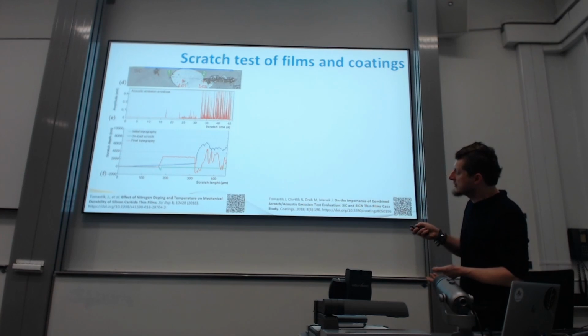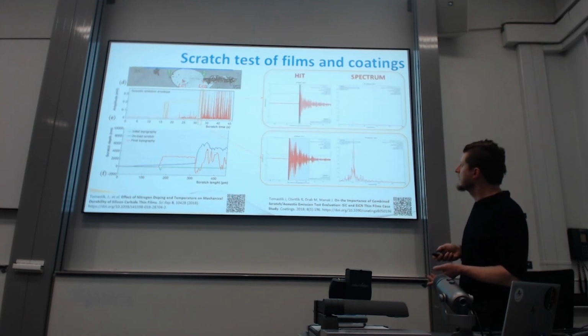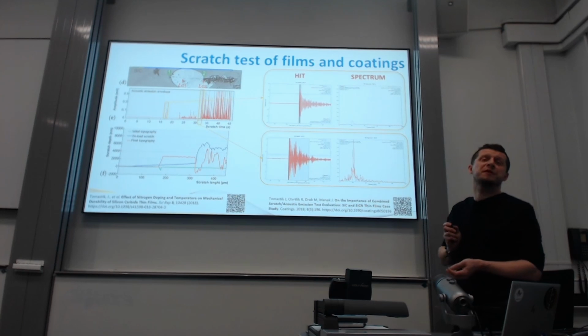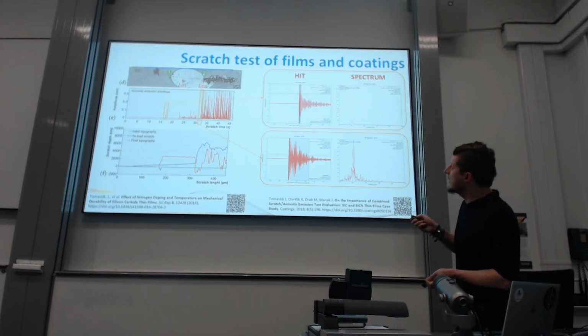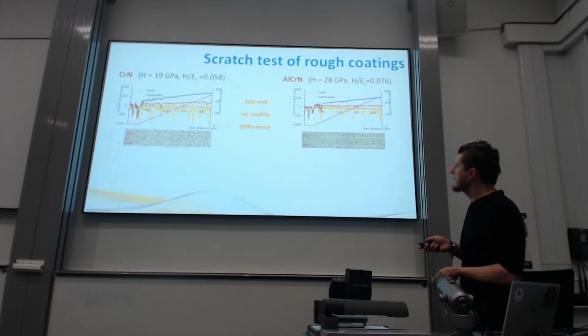But here you can see, so what happened actually? There was some debris, it broke, and then the spallation occurred from that point backwards, because the final topography shows the spallated or delaminated substrate. Actually, the first critical load occurred at this moment, where the substrate is cracking. And you can also use the advanced method to analyze the hit shape and spectra. So this is what can be helpful.